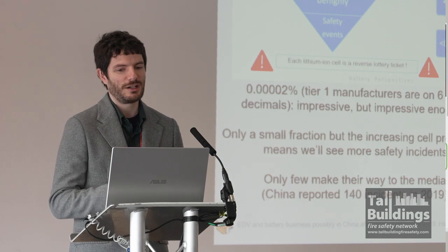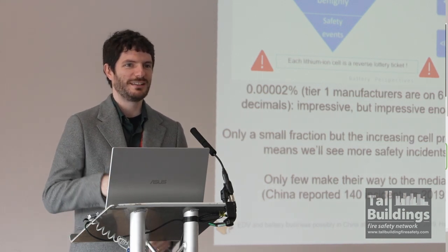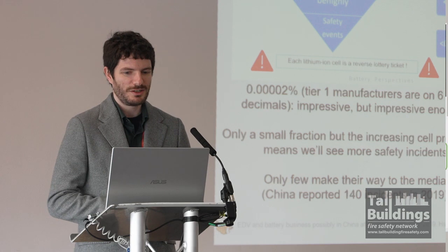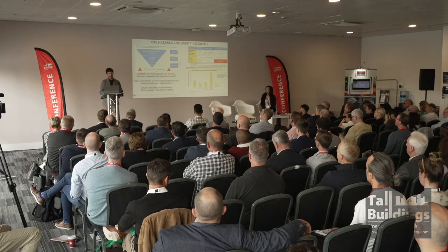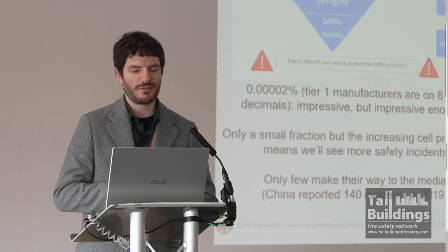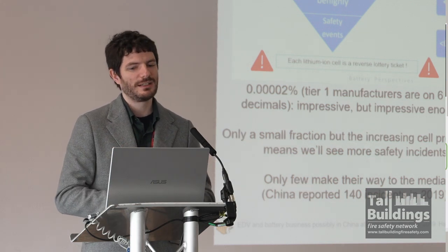The amount of energy each cell can release is very high. You get about nine kilojoules from the decomposition at the beginning for the 18650 — that battery that looks like a double-A, just a little bit thicker. But once you start having combustion of those gases, you're getting 90 to 100 kilojoules of energy per cell. The auto-ignition temperature can be about 450 degrees. You might have gases spreading and not igniting — at 80, 100, 150, 300 degrees — but as soon as they reach 450, they auto-ignite. That's a lot of energy being produced.